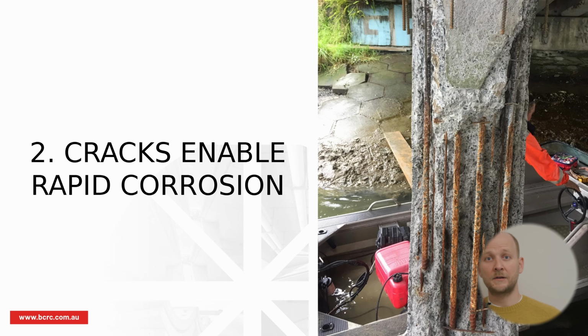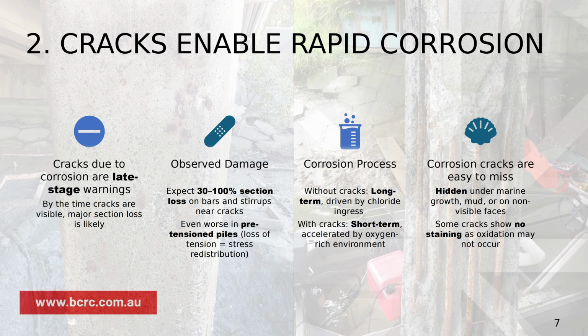Now let's talk about cracks. I would like to focus on a particular type of crack induced by corrosion. And when you see these cracks, it's a late warning. So by the time you see these cracks, the corrosion is going on, and you're likely to see section loss at 30 to 100%, with quite often a lot of stirrups being completely gone.